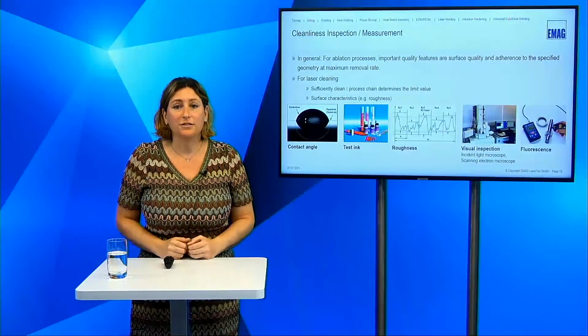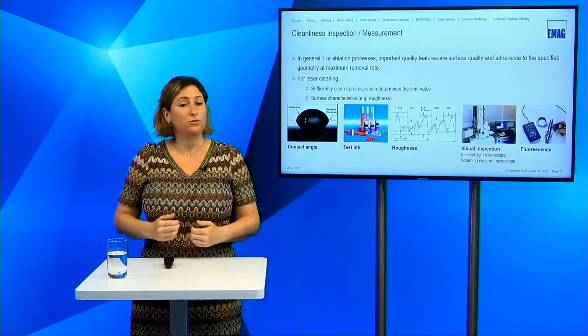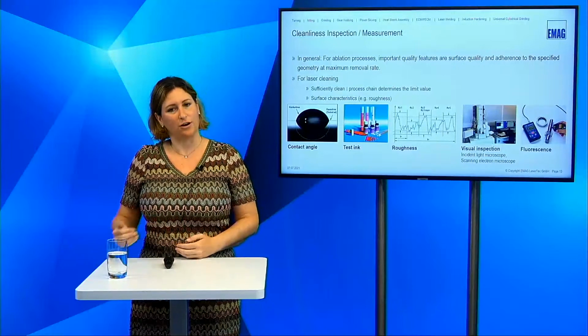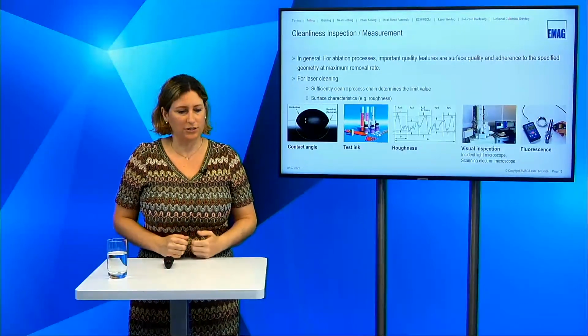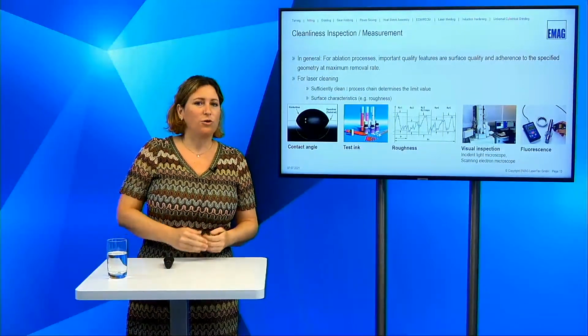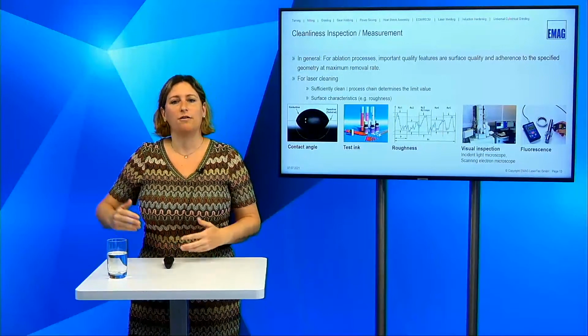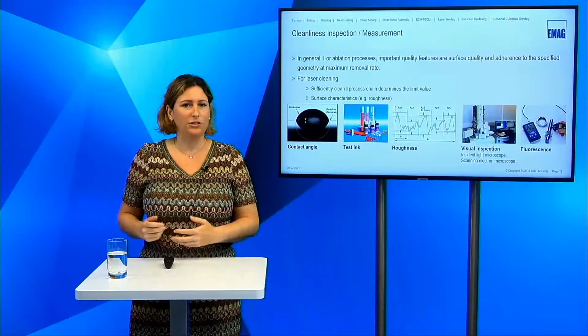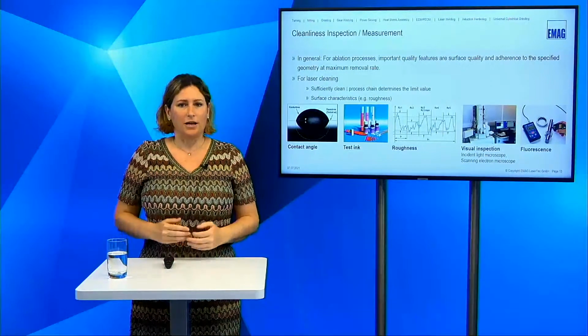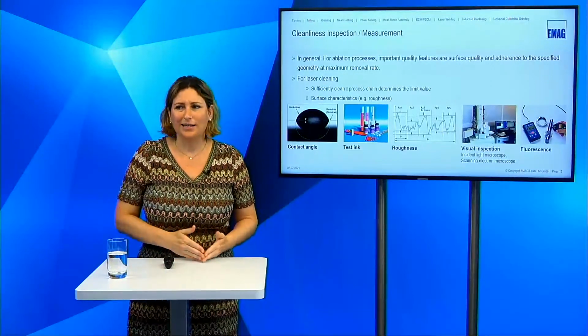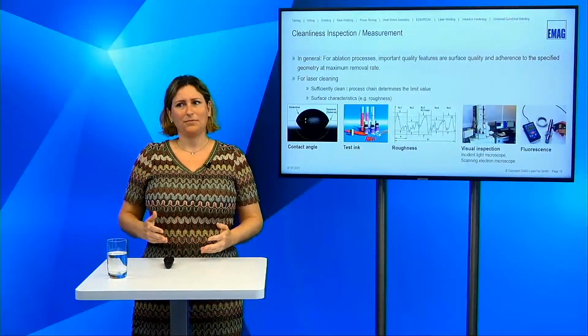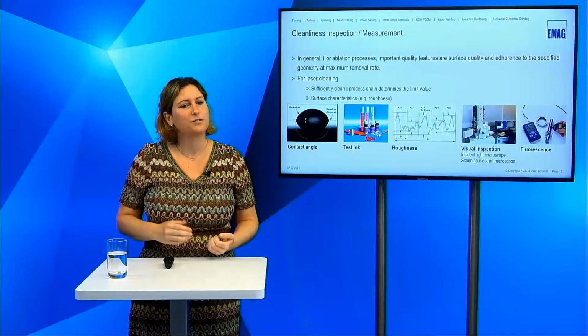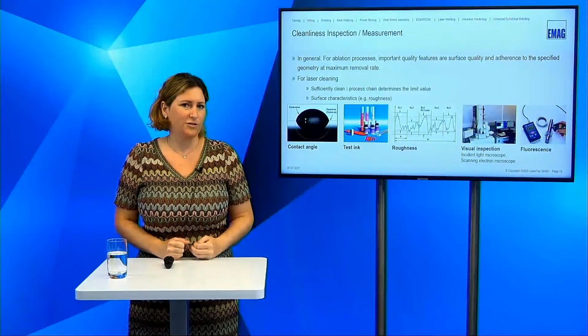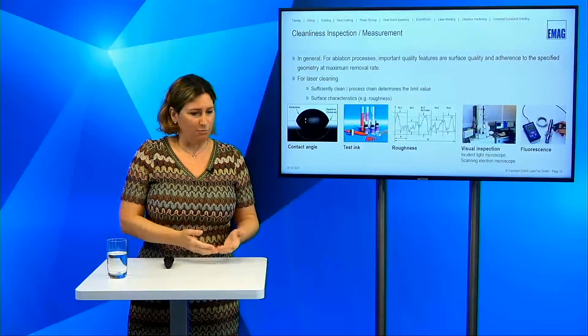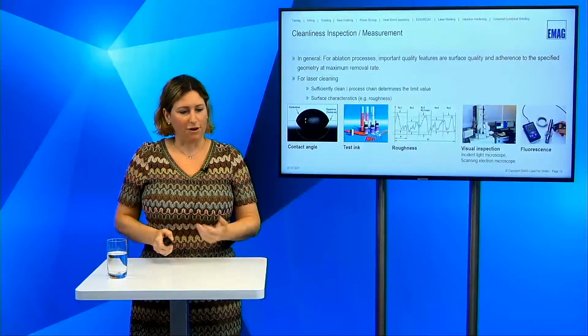Also, the roughness is quite important because you don't want to hit the surface that much. So you check also if the roughness is still okay. Sometimes you also want to increase the roughness because you have following processes which need an increased roughness. At least the laser cleanliness is a value which also is influenced by the following processes. So sometimes it is important or it is not important to have a roughness or not.